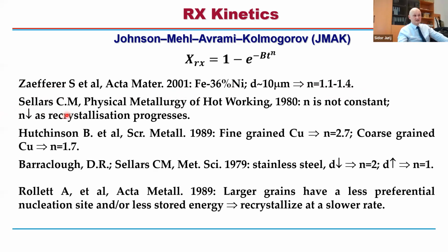Then a group of Sellars, basically in the 1980s, claimed that n is not constant and tends to drop during the recrystallization process. Davies and Hutchinson in 1989 claimed that in fine-grained copper and coarse-grained copper, n was in fact varying. So for the same material, identical conditions, the only difference was working with fine-grained material in one case and coarse-grained material in the other. So this n seems to be sensitive to microstructural features.